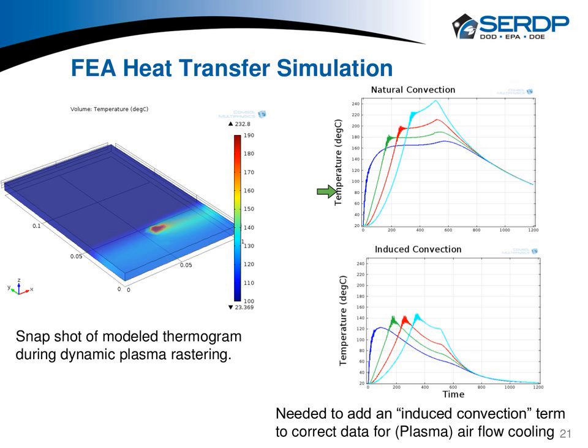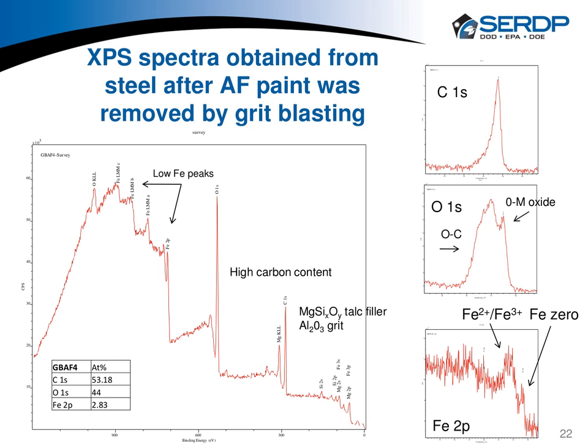When we first ran the profile, we found that the measurements did not exactly match what we were attempting to achieve. It wasn't until we had to force a second term into the model for induced convection that we got the same results theoretically that we achieved experimentally. That was a very important discovery for us because we had originally thought we might need to use some hybrid technologies if necessary to aid in paint removal. So what this demonstrates is that, if necessary, upon scale up, there could be alternative systems added that will help us resolve any type of thermal issue that may be present or not.